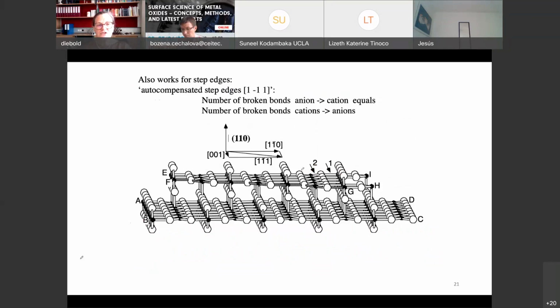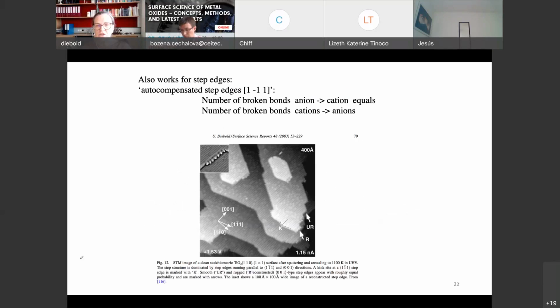You can even predict how steps look. So this is on this TiO2 surface, where we have the titanium atoms and oxygen atoms sticking out. This is how, from the simple rule, one predicts how a step would be oriented in the 1, 1, 1 direction. And this is the STM image. You have these rows of the oxygen atoms, and these are the steps that you can see. All steps have similar orientation. They're all in 1, 1, 1 orientation.